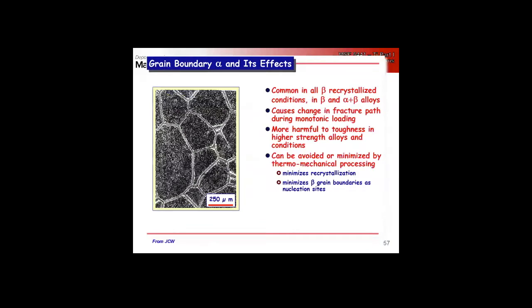Okay. So grain boundary alpha. The big problem is a loss in toughness, because now we've got clean, connected, percolating fracture paths through our structure along the grain boundaries. So the key things that we want to avoid: minimize our recrystallization and minimize the beta grain boundaries as potential nucleation sites. If we want to avoid grain boundary alpha, we need more potent nucleation sites than the beta grain boundaries.